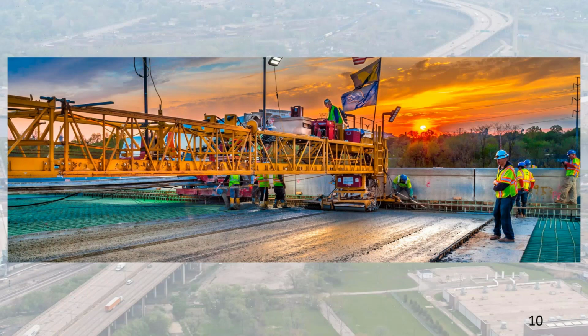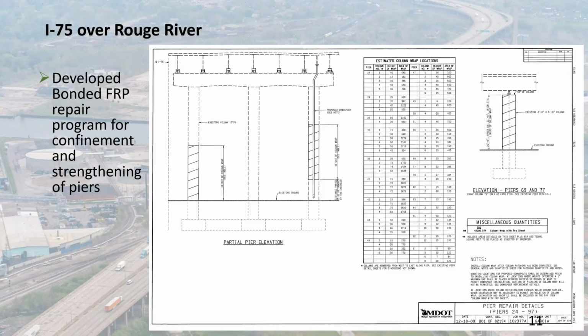So, what we decided to do with the forest of columns and piers that we have supporting the superstructure, we've had issues. These particular concrete elements contain slag aggregate, which Steve is going to talk about why that's an issue in a minute here. So we did a very comprehensive sounding and scoping process for all of our piers, and we developed the plan sheet that you see here for a program of using FRP systems for confinement of these columns. And as you can see, this applies to piers 24 through 97. We didn't work on all of them, but you can see from the table, we worked on a significant number of these piers, some of them approaching 90 to 100 feet tall.